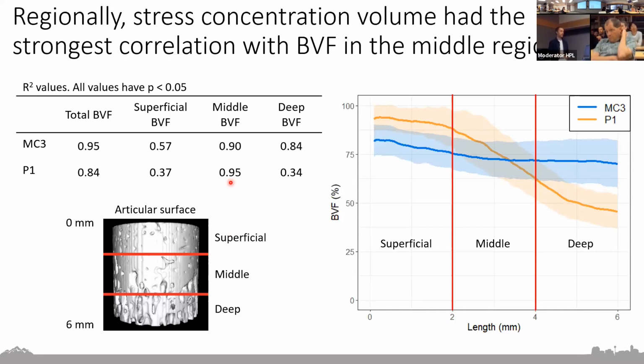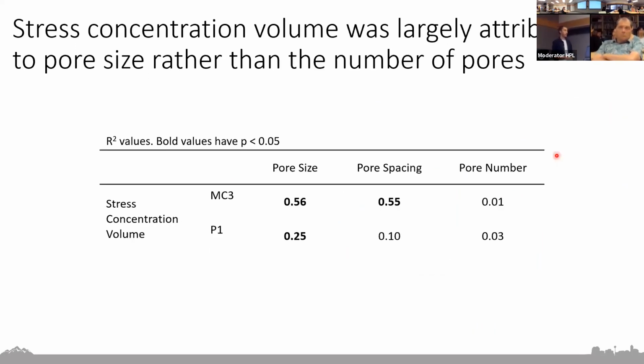So we're still working through some more exploratory analyses with this, but so far we found the later that it transitions into the trabecular bone, sort of reflecting a thicker cortical plate, that improved fatigue life. And we're still looking into that a little bit more. And then for some of the microstructural parameters, we found that stress concentration volume was largely attributed to pore size rather than the number of pores. So there really wasn't any relationship with the number of pores present in these samples, but we did see some nice correlations with the size of the pores present.